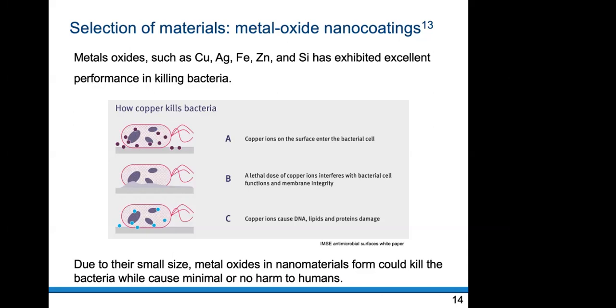And there are some concerns in using the metal oxides because they are also reported to have an adverse effect on human DNA. However, if we are using the nanomaterial form, we are using only a small concentration of the material and still be able to achieve the performance levels as high as we want. For example, if we use a coating, instead of the whole material, we can use only about 1 to 2% of the coating or up to a maximum of 5%. Because of this lower concentration, we wouldn't experience that much adverse effect.